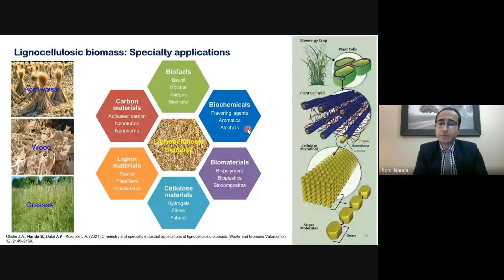Biomaterials can be extracted, for example, the biopolymers themselves, like cellulose, hemicellulose, and lignin, can be extracted for application in bioplastics and biocomposites, and the cellulose can be used as hydrogels, as cellulose fibers and fabrics, textiles. Lignin material can be extracted for application in different resins and plasticizers and antioxidants because lignin is hydrophobic in nature. Because of the hydrophobic and elastic properties of lignin, these applications are mostly identified in different commercial industries. Lignocellulosic biomasses can be carbonized to produce different carbon-based materials like activated carbon, carbon nanohorns, carbon nanotubes for different high-value or high-end applications that rely on carbon materials.